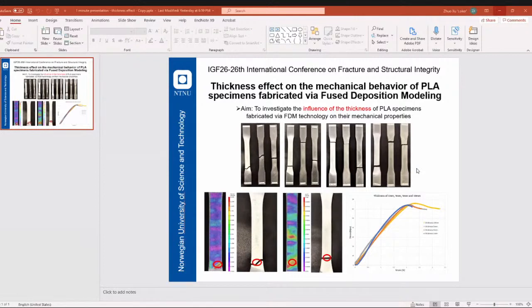Usually when you have this type of 45 degree angle failure along the fibers, that shows that you have a possible weak bonding. So this proves what you were mentioning before, that most probably there have been higher defects in thinner samples. This is probably something that you can study better by doing some SEM analysis on the fracture surface and correlating it to the observations that you have done.